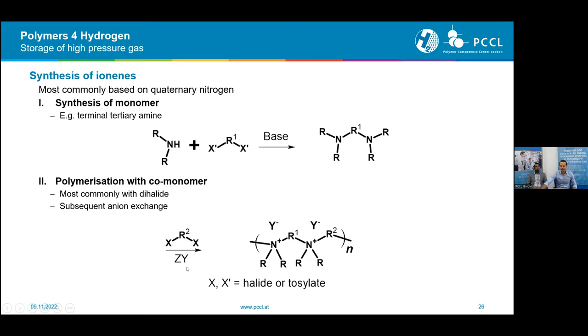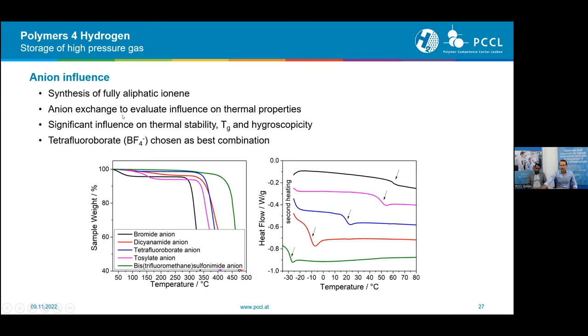And initially, it gets the halide of this co-monomer. This anion you can then just exchange by adding a salt with the desired anion that you would like to choose. So the first polymer that we synthesized here was fully aliphatic, so similar to, let's say, polyethylene in the chemical structure. So it is only linear chains.